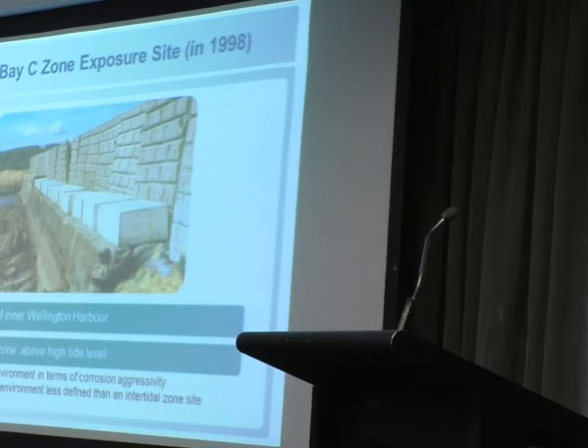And I remember when we first set this up, I was very disappointed. I thought that what was required was a site where the blocks would be tidally inundated, so you knew how much chloride loading they were receiving every day. But I guess the advantage of this site is the concrete is getting splashed by the waves, but it's also an environment where lots of oxygen is available. And typically, if you go out and observe reinforcement corrosion deterioration on marine structures, that's what you see. It's worst above the high tide zone.